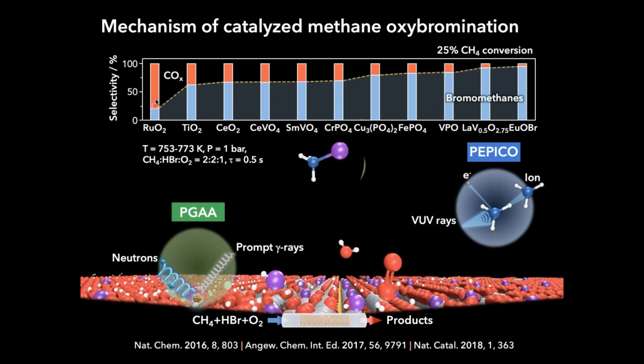So we start with a very low selectivity to the desired products. This is in blue here. These are bromomethanes. Undesired is carbon dioxide. We start with very low selectivity because ruthenium oxide is highly redox active. So it's going to oxidize HBr, but it's also going to oxidize methyl bromide into COx. And you see the evolution moderating the redox properties of the surfaces so that we reach optimal values with europium oxybromide or lanthanum vanadates, where only 2 or 3% of selectivity goes to carbon dioxide and about 97 or 98% goes to the desired products. So this is an example of using sophisticated techniques to drive catalyst design as well as catalyst development.